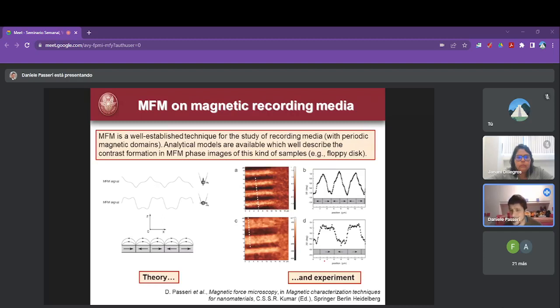Now, up to now, this is exactly what I told you before. You watch, you read the papers by other groups. Everything works. Everything is perfect. We said, okay, let's start with the magnetic recording media. For this kind of materials, magnetic force microscopy works perfectly. You see, for instance, just an example. According to the model, you expect this profile, this is the floppy, with a tip vertically magnetized. You expect this profile with the tip horizontally magnetized, and the experimental results fit very well with the theory.